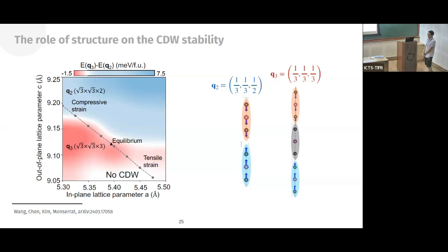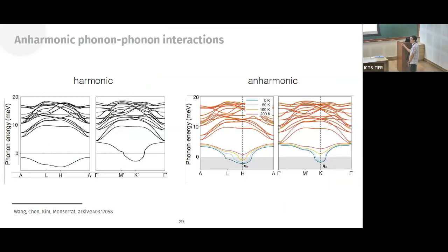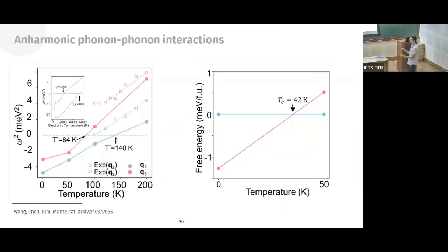Speaking of things that can change the C lattice parameter, is there a reason to be worried about thermal expansion in the system? Does it change C appreciably in this plot? Absolutely. Thermal expansion is, of course, something else that can do that, and we did include that in our finite temperature calculation. For example, when you do the self-consistent harmonic approximation, your variational parameters are in fact not just the wave function itself, but also the positions of the ions and of the lattice. So you can take fully into account thermal expansion. That's what we've done here.